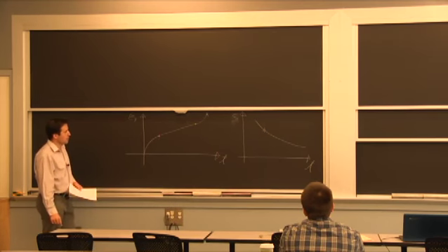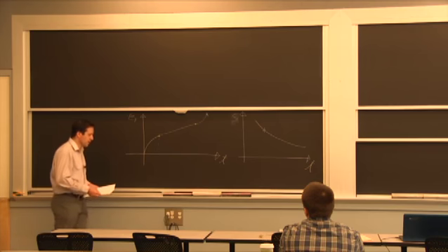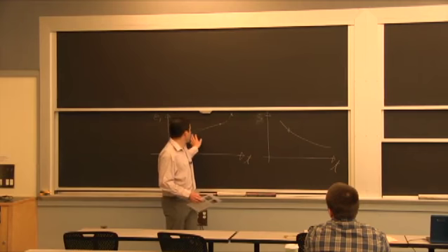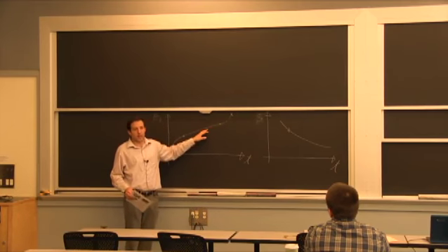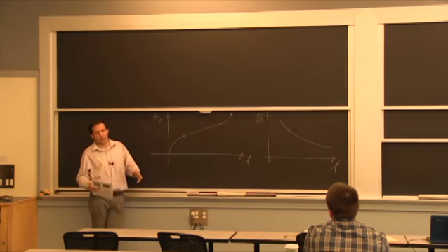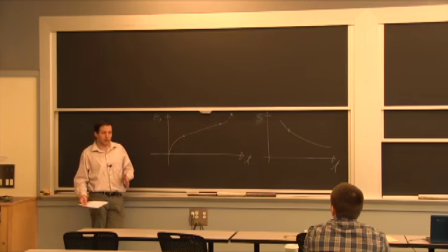What I would say right away, we're going to talk a little bit about alloys that are used for turbine engines. And what happens there is you're more limited by the amount of strain that you can tolerate in your design than by that fracture. Not in all the conditions, but there are blades that fit so tight in the shroud that if they elongate 2%, now you have a big interference.